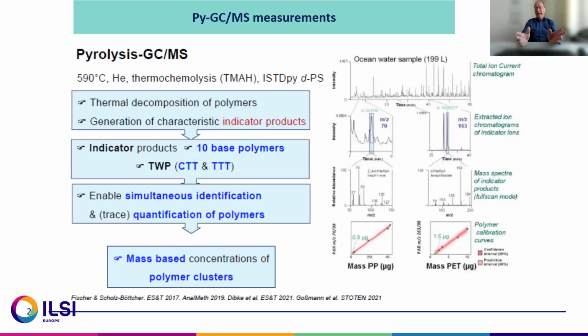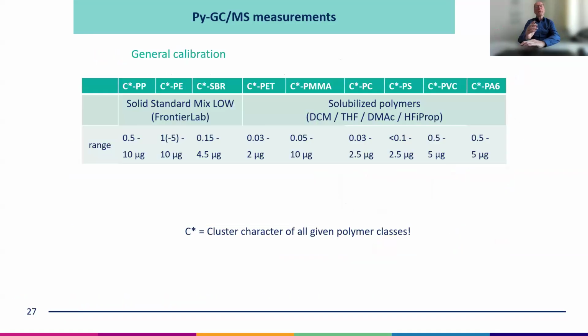Then you have identified the polymer, but what we also want is a quantification, and for this quantification, you need a calibration with internal standards and so on, and this can also be very time-consuming. At the end, you have the mass-based concentration of polymer clusters. Because we do not have an indicator for every polymer, we have to generate so-called polymer clusters.